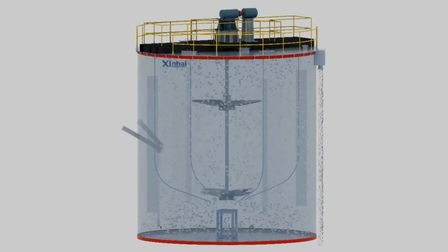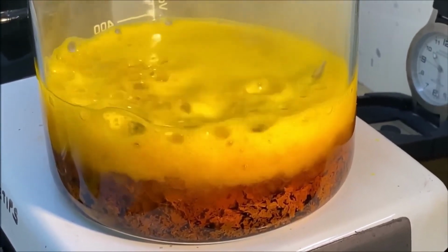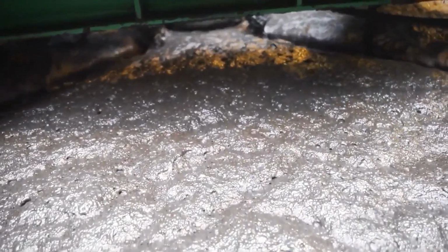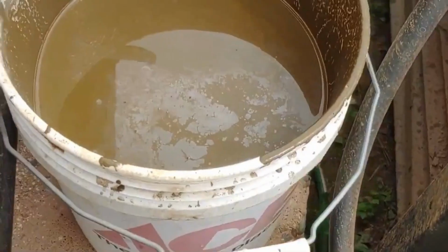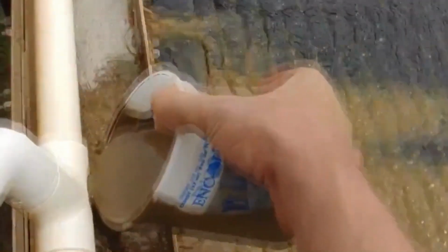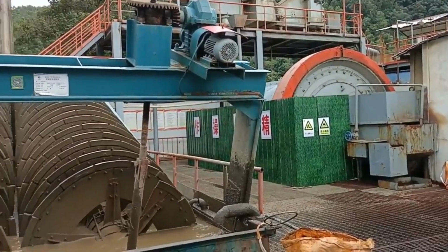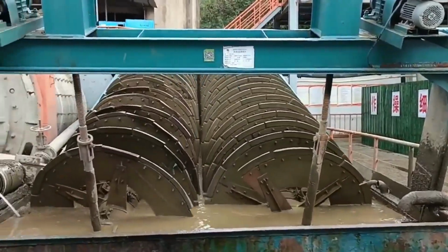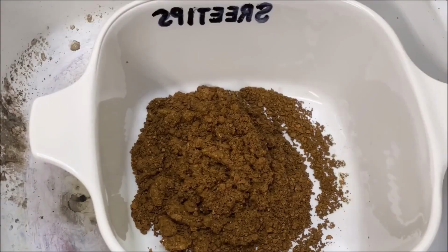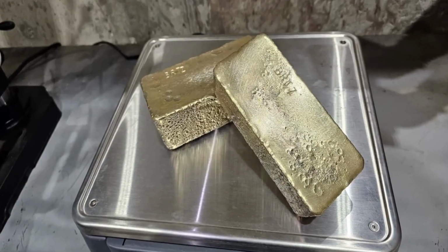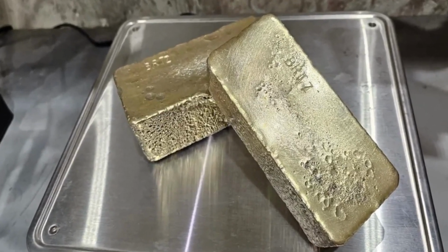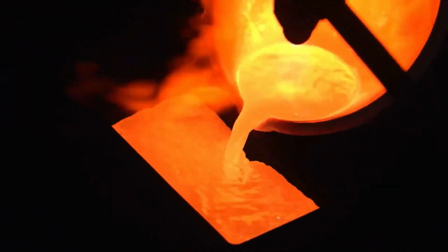At this stage, the gold is dissolved in the cyanide solution, so it is recovered through a precipitation process. A reducing agent, commonly zinc powder, is introduced, triggering a chemical reaction. This reaction causes the gold to be released from the solution and precipitate as a golden sludge or powder. During precipitation, other elements, such as silver, may also precipitate if present in the solution. The result is a gold-rich mixture collected and then filtered to separate the precipitated gold from the remaining liquid. This golden sludge is the precursor to doré, an impure gold alloy refined in subsequent stages to achieve high purity.